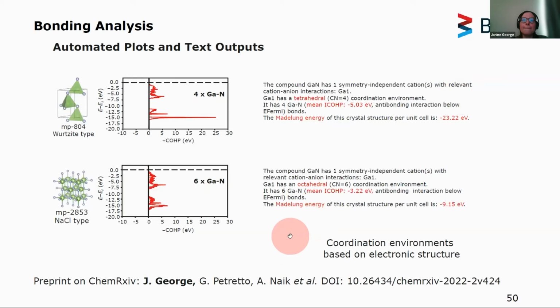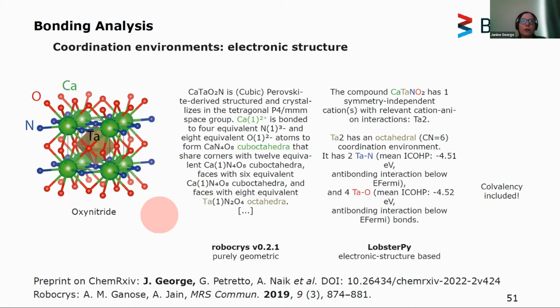Just also to illustrate this difference between coordination environments from the electronic structure and those based on geometric approaches, I'm taking this oxynitride structure here. So you have calcium in a 12-fold coordinated environment, tantalum in an octahedron. And if you use a purely geometric-based code, for example, Robocrystallographer, that I very much like, and that is also, of course, available on the Materials Project, then you would get calcium is coordinated in a cuboctahedron and tantalum in an octahedron. In contrast, LobsterPy will only find the octahedral environment of tantalum because the calcium-oxygen and calcium-nitrogen interactions are very weakly covalent. So we get actually a complementary picture to this purely geometric approach.